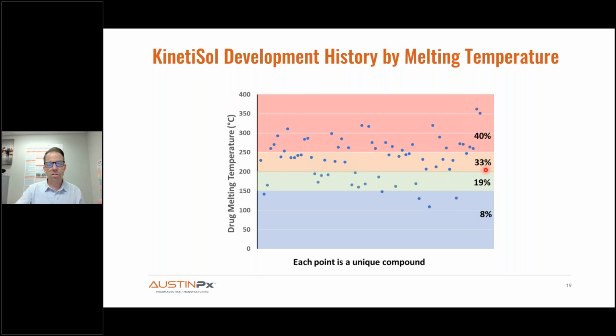The next is being able to solubilize high melting point compounds well below their melting temperatures, which is also unique to kinetisol over melt extrusion. And I generated this figure a few years ago just to show the range of melting temperatures that we've successfully developed products in over the years. So what you see is about 3/4 of what we worked on would be considered high melt, 200 degrees C and above. And I'll point out some of these here more recently where these molecules have melting temperatures north of 300 degrees and even north of 350 degrees. So these are ultra high melt brick dust compounds. You wouldn't dream of trying to melt extrude these to any reasonable drug load, but these are routine for kinetisol.